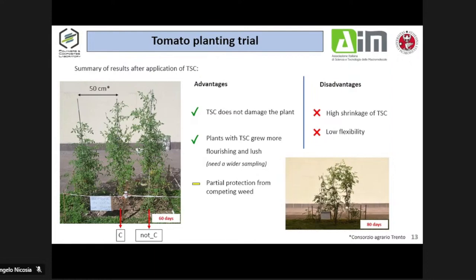We have partial protection from the competing weeds in the case of cross-linked material, but we have some drawbacks regarding the shrinkage, because the material was cyclically stressed by water absorption and desorption. At every desorption, there was a shrinkage. And we also have problems with the flexibility.